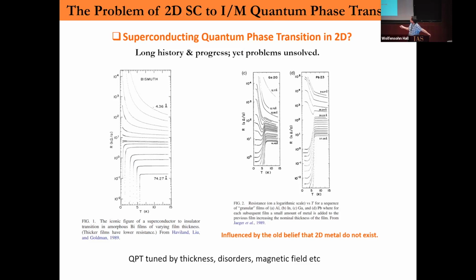So one of the perhaps very important data sets is like this: a superconducting transition in a two-dimensional thin film, from the superconducting state to an insulating state. So the 2D superconductor to insulator transition. This is induced by reduced thickness of the bismuth film, and also many, many other measurements for different materials. The data is not every time the same. So it's not universal.